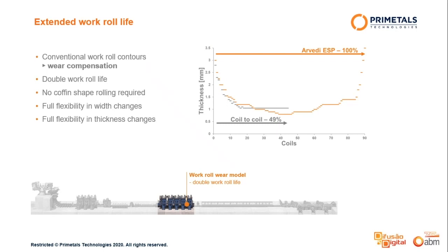Due to the perfect shaping of the intermediate strip in the high reduction mill, the finishing mill can be run with conventional work roll contours, which allows then wear compensation. This leads to double work roll life campaigns compared to coil or batch processes or batch operations. This is an essential operational cost factor. So ESP does not require coffin shape rolling and is fully flexible in width change decisions, as well as in thickness decisions. Someone could now think that the coil-to-coil mode supported by a tunnel furnace would be helpful or essential, but